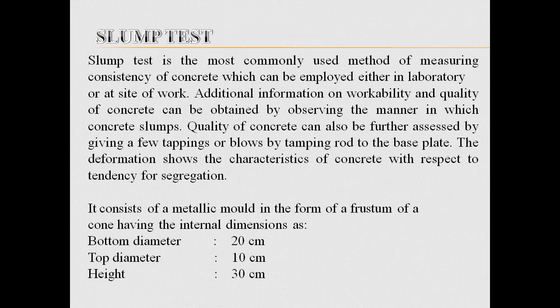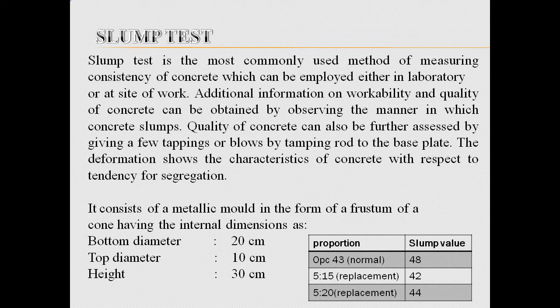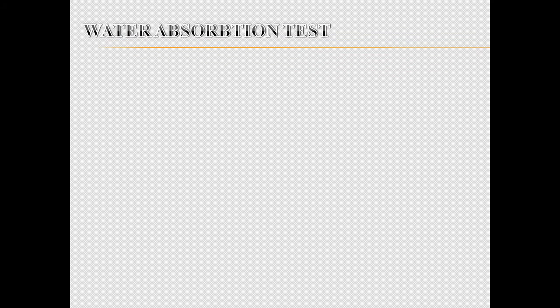Slump test. We obtain a slump of nearly less than 50 for all concrete mixes. The slump test is a method for finding the workability of concrete. It consists of a metallic mold in the form of a frustum of a cone, having the internal dimensions of bottom diameter 20 cm, top diameter 10 cm, and height 30 cm. And we got all the slump values since it is an M40 grade.